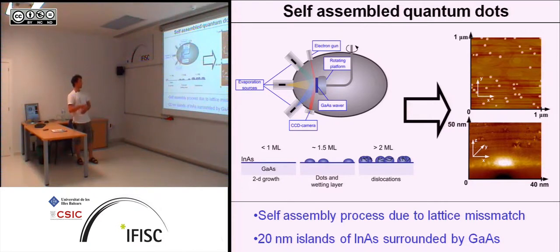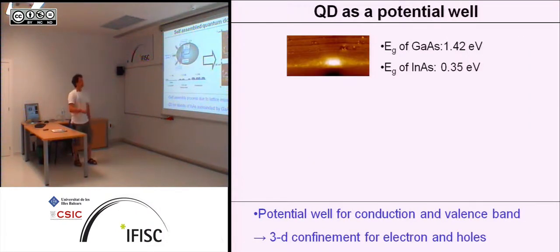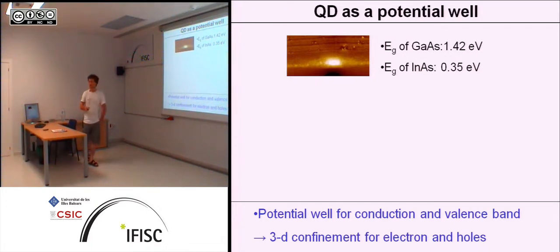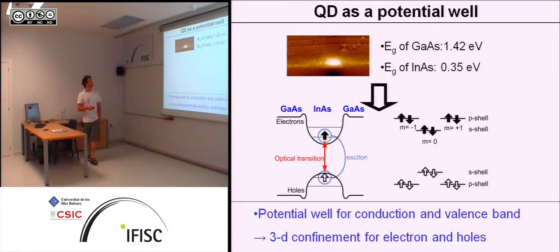The other thing is that you have a 20 nanometer, more or less, sized island of indium arsenide surrounded by gallium arsenide. The interesting bit now is if you look at the band gap energies: for gallium arsenide you have 1.42 electron volts, but for indium arsenide you have 0.35. What that means is that you actually have a potential trap, a potential well in all three dimensions for electrons as well as holes.